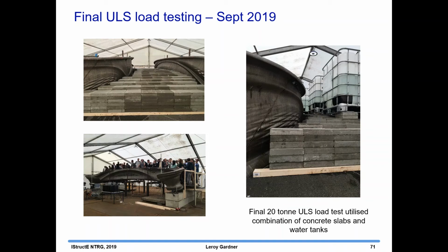So initially what we did is we applied 4 levels of these concrete blocks. That corresponded to just under 10 tons of loading, and we were putting these on manually, one by one, in a controlled sort of organised pattern so that we kept the loading approximately uniformly distributed. So we were on the bridge at that stage, so we didn't want to be at loads that were higher than we'd been to before.